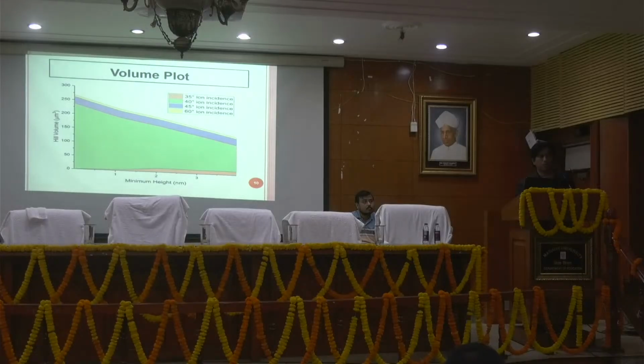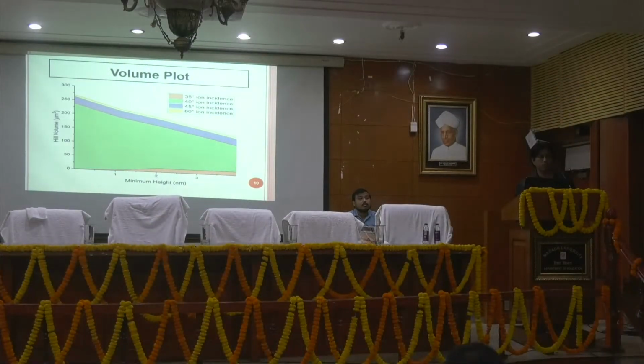Now the volume plot. We have also calculated the volume at different angles of incidence, and we see the green portion represents the maximum area coverage. So a 45 degree angle is appropriate for the ion beam incidence.